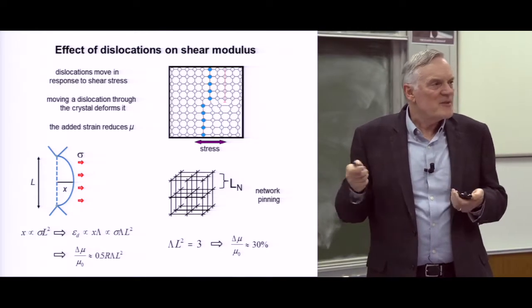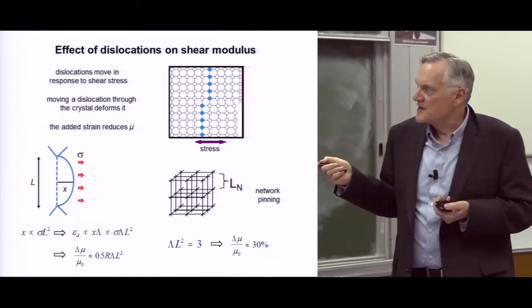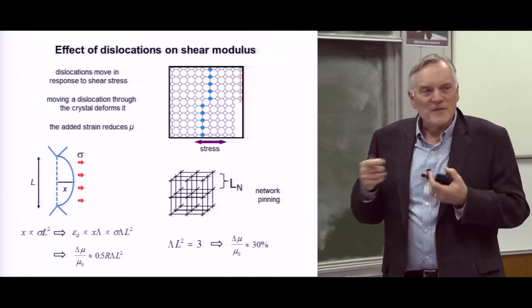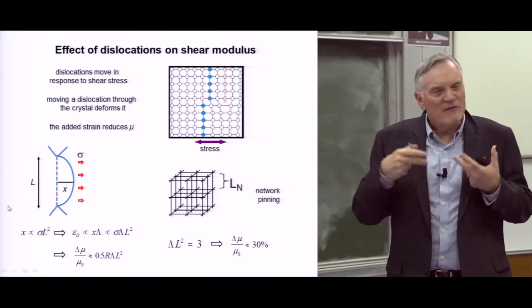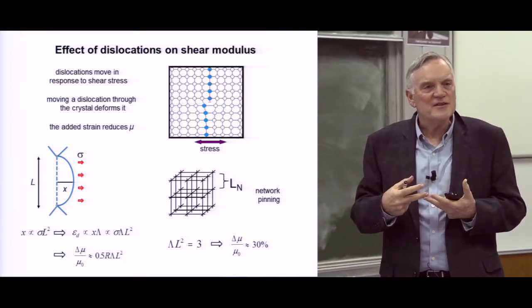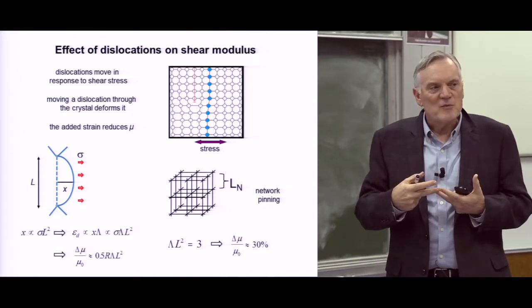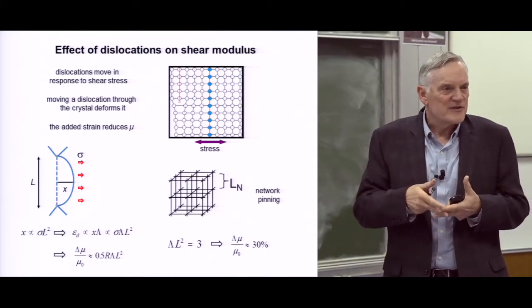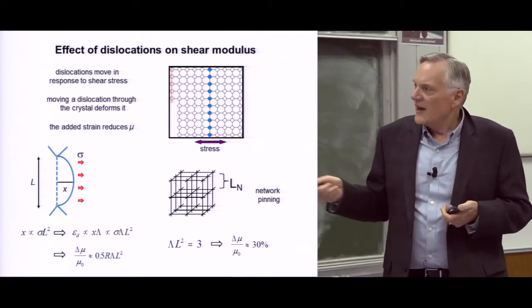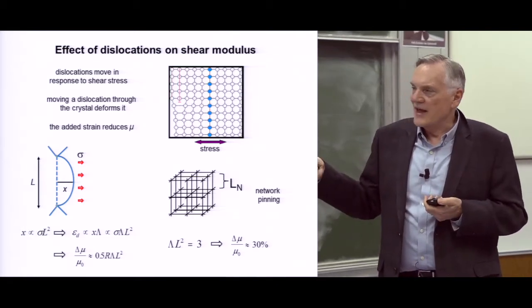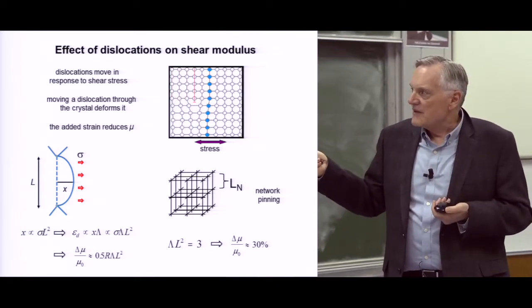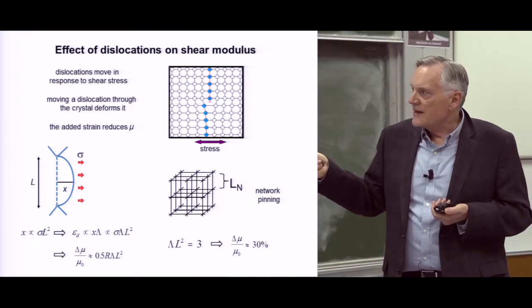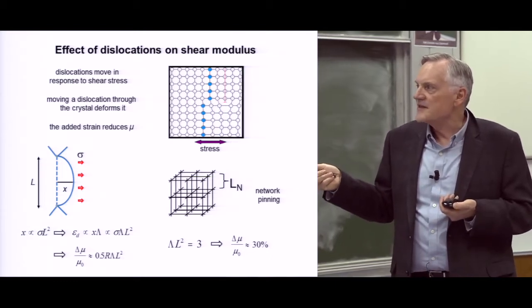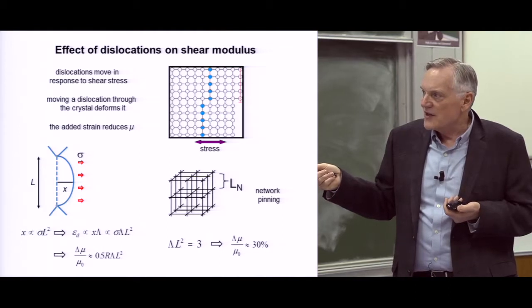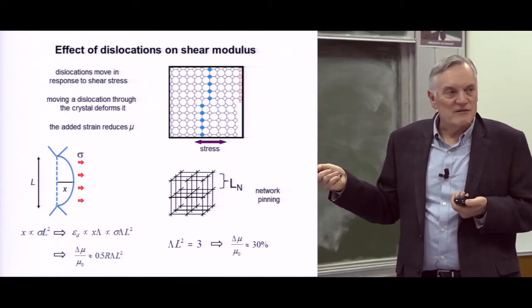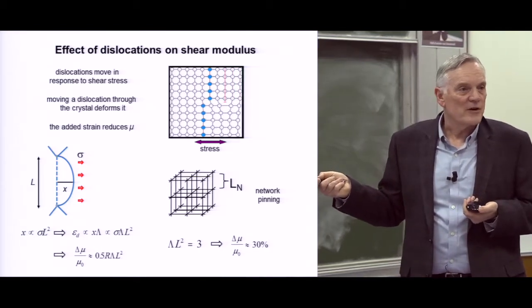It can be 10, 20, 30%, much, much more than is ever seen in a metal, but it's possible. And the reason is because they do make a network and they pin each other. And if you have a high density of dislocations, that doesn't mean necessarily they have more effect because they also pin each other more. They intersect more often, they're shorter. And it turns out if you take something really simple like a cubic lattice just to see what the effect is, there's a network length between pinning points and a total length of all these lines. And this combination, the one that tells you how much the shear modulus drops, is actually just 3. It's just a number for a cubic lattice.